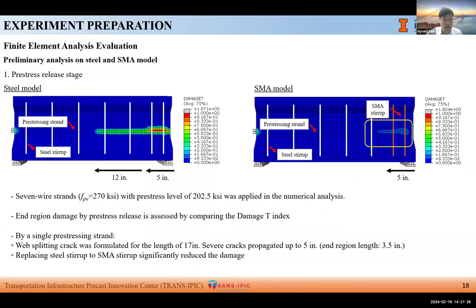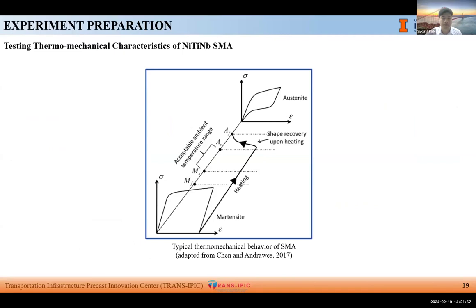Preliminary numerical analysis was performed in the scaled-down model as seen in the figures. Focusing on the crack at the web, we could see significant effect of crack mitigation in length and width by applying only 2 SMA stirrups at the end region. By referring to the results, the SMA effect was proven, and we are now in progress for experiments with diversifying variables such as number of SMA stirrups, SMA activation method, and the location of SMA stirrups.